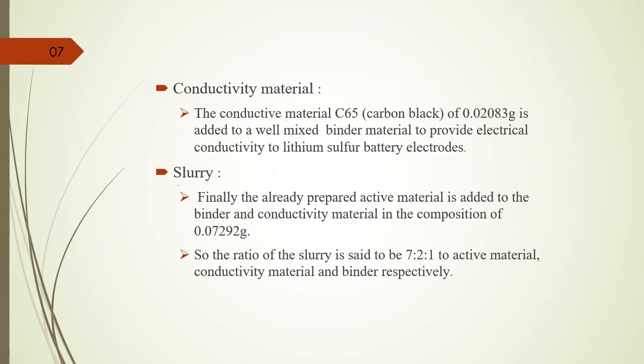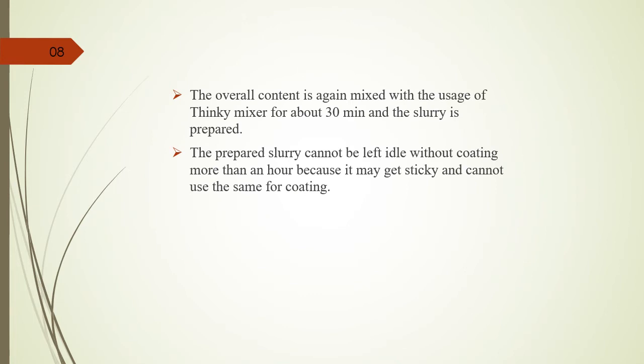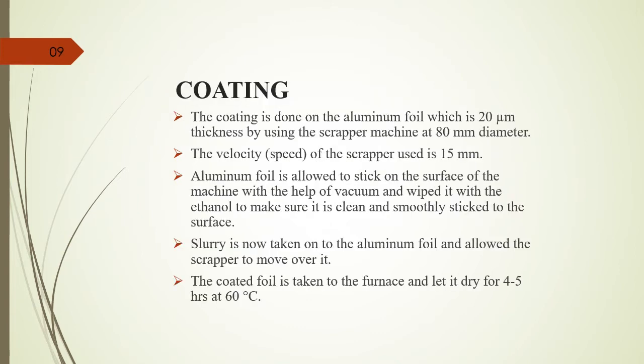So finally the slurry. I prepare the slurry by combining all the above three steps in the ratio of 7:2:1, where 7 is the active material composition, 2 is the conductivity material, and finally 1 is the binder, for which I used PVDF. I make the slurry using a mixer for 30 minutes to mix this composition well, and we get a sticky liquid type slurry, and I use that slurry in the further process. The further process is coating.